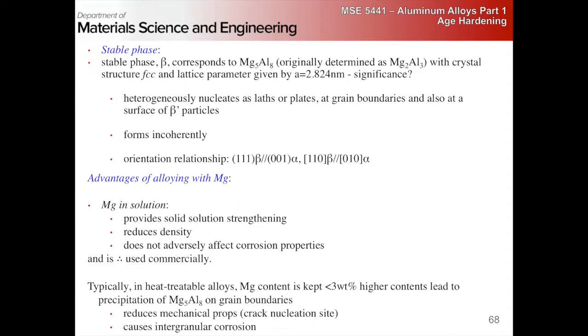They built a bunch of ships 20 years ago using magnesium-containing aluminum alloys, and then left them in the tropics for several years, where the temperature was hot enough and the kinetics just fast enough, so over that period of time, grain boundary beta was growing. And now they're having huge problems with stress corrosion cracking because you're in salt water, in a horribly corrosive environment.